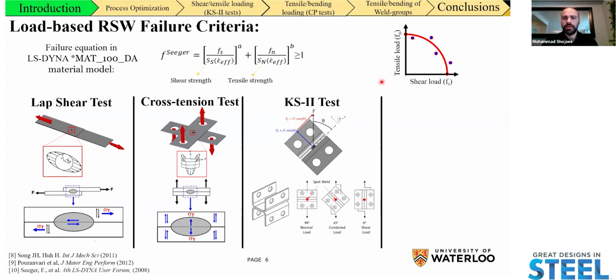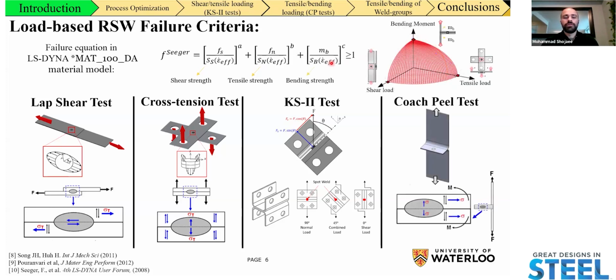Now, what ended up happening a few years after Seeger suggested this equation is they actually added a third term to their initially proposed equation, where they essentially transformed their 2D failure contour into a 3D failure surface. This third term deals mainly with bending strength of the spot welds that is commonly characterized by the Coach-Peel test. The Coach-Peel test, I've shown a schematic of it here, where there is an offset between the loading axis and the location of the spot weld.